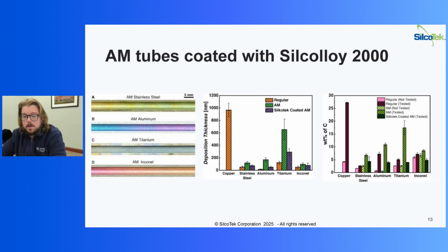But as a result of coating these tubes, you can see in the middle graph here, every single one of those additively manufactured tubes had thinner deposition thicknesses of the carbon deposits after exposure to the jet fuel. And interestingly enough, on the right-hand side, rather than just looking at how thick the deposits were, they actually looked at the weight percent of carbon on the surface of these materials. And you can see essentially what we're looking at is we really want to compare the dark red with the dark green and the medium green.